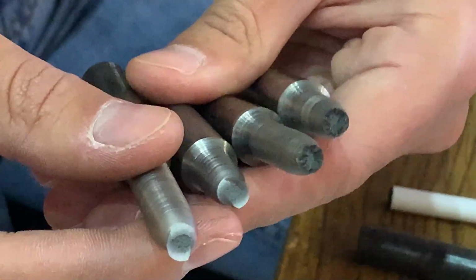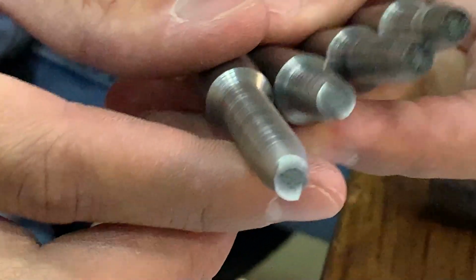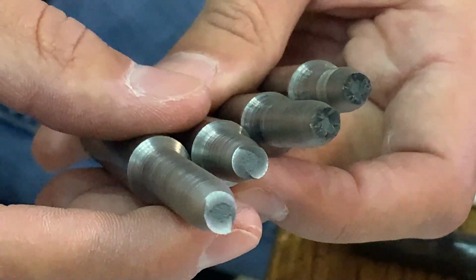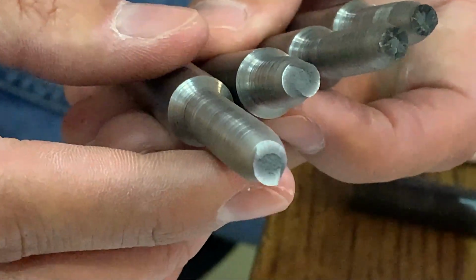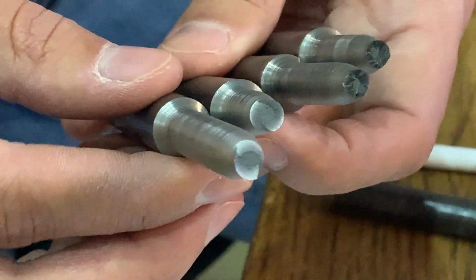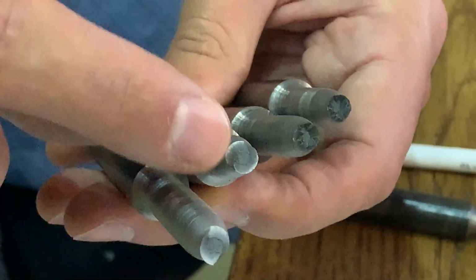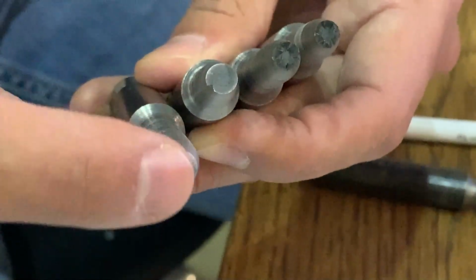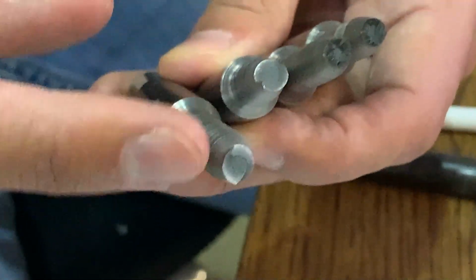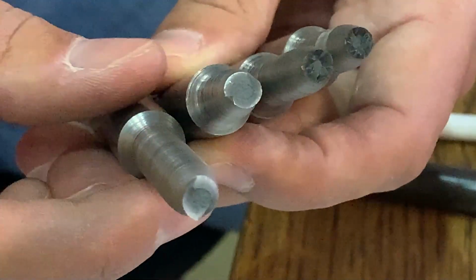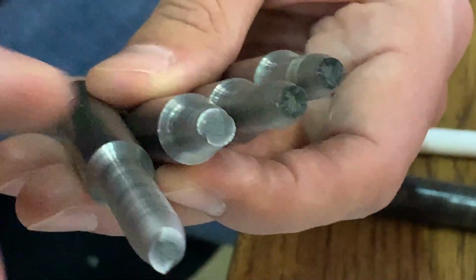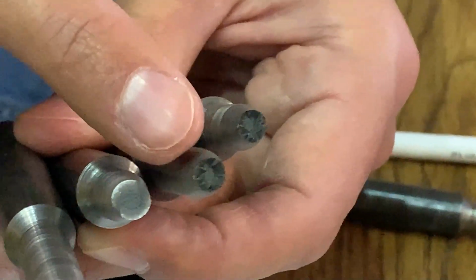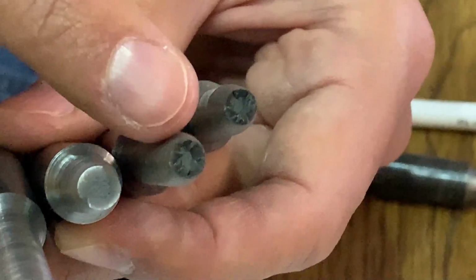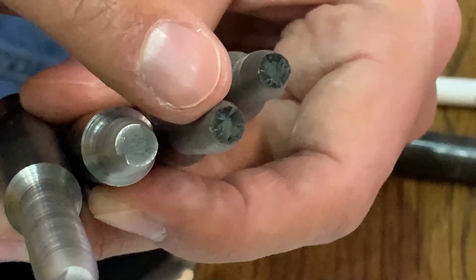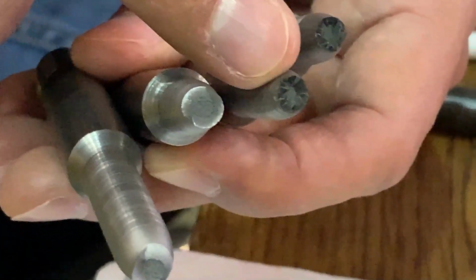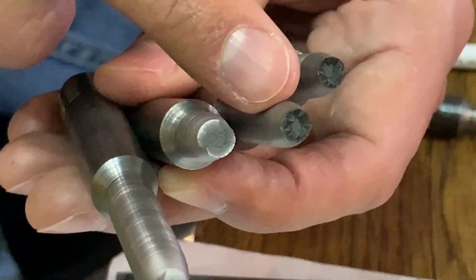What we have on our 1018 steel is what we call a cup and cone, and that is more prevalent to ductile material. And we can see a formation of that cupping happening on the edge or the circumference of where the material failed, compared to our 4140. Our 4140 has more jagged peaks, hills and valleys, as I would call it, being more characteristic of brittleness.